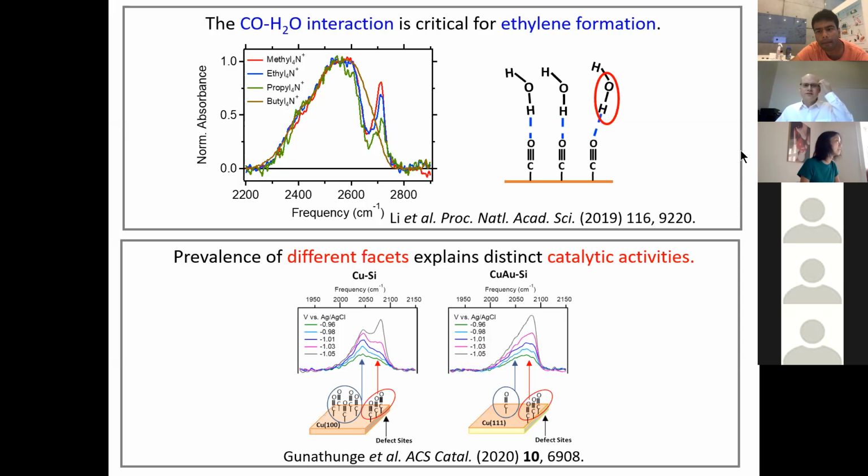Yes. So the mechanisms are quite different. Here we have organic cations that, based on the spectroscopy, have a very specific impact on the water. Specifically, the largest cation, tetrabutyl ammonium, is supposedly quite hydrophobic. So when it gets attracted to the electrode, when we go more negative in potential, it expels water. So I see here that's more like a hydrophobic effect, or it has this impact on the structure of water that the alkali metal cations that were used by Bell and co-workers do not have. So there's an additional interaction in these organic cations that is just not present for the alkali metal cations.